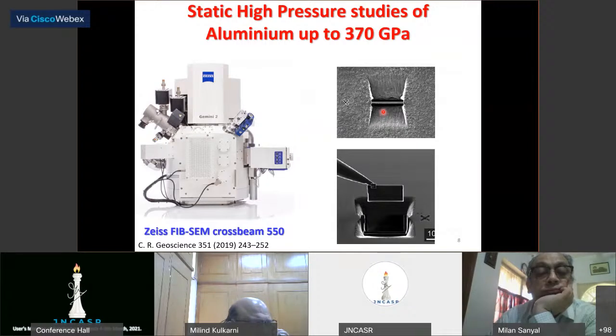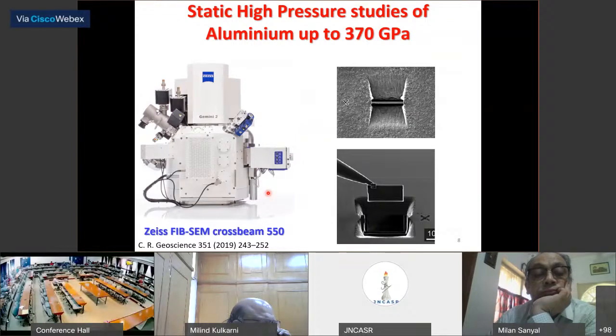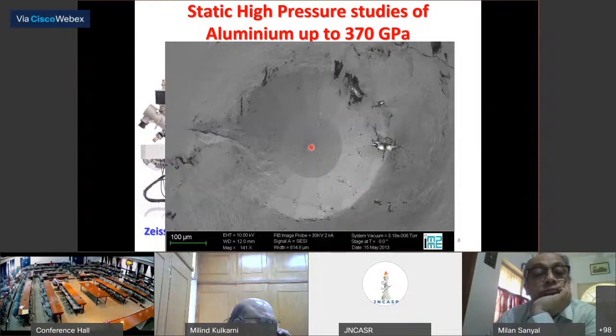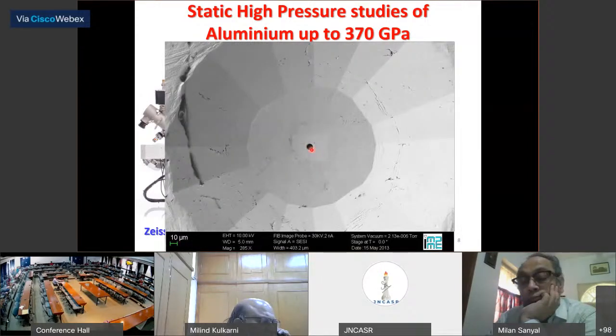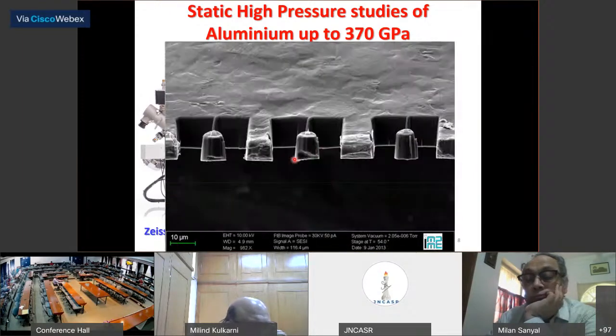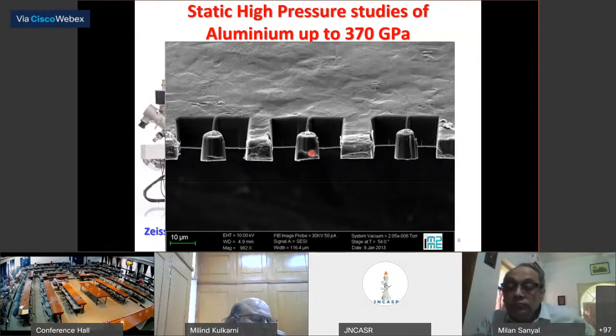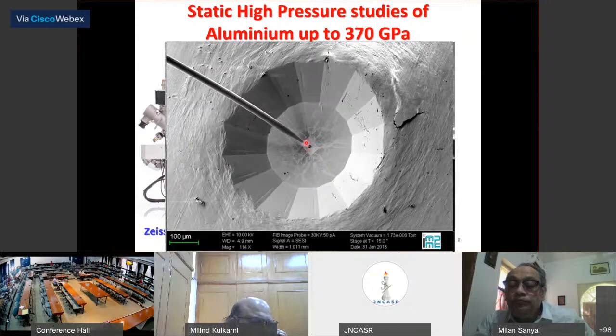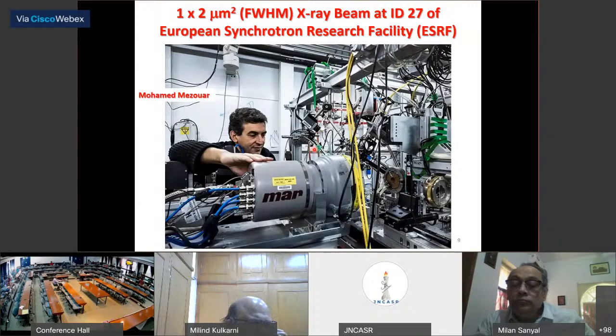Today, we can actually make such tiny samples using focused ion beam, which is generally used for TEM measurements nowadays for making lamellae. So we use that to drill a hole of about 10 microns. You can see this is the 10 micron hole in this gasket. And in this, we can actually place this aluminum foil, because we cannot take aluminum powder because it is pyrophoric. So you machine these nice little structures, and you can put them inside the FESEM itself. And then you go to a synchrotron.